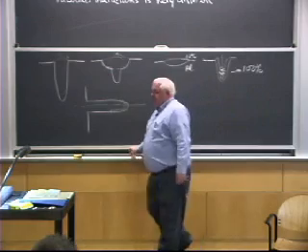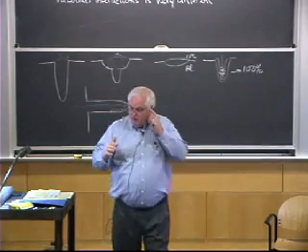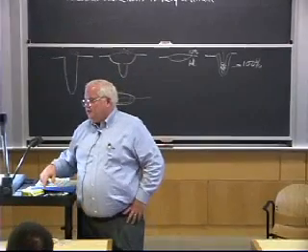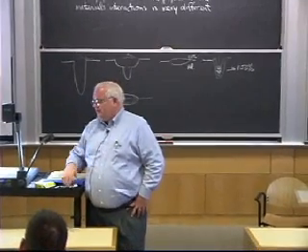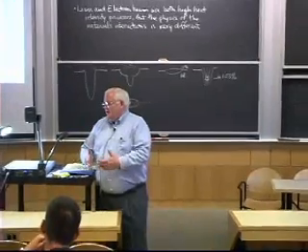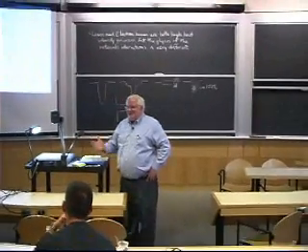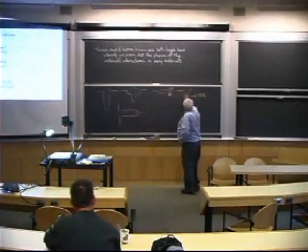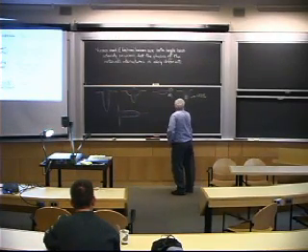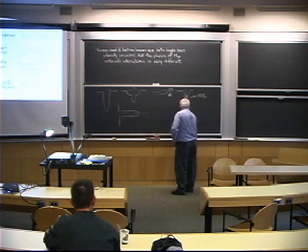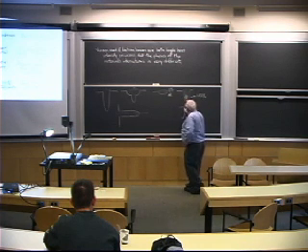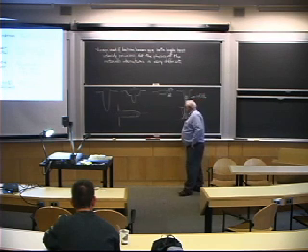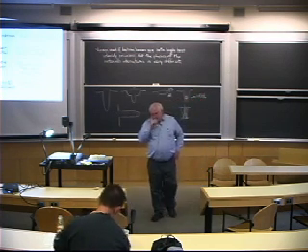So we did some experiments once years ago on laser welding of aluminum, and we showed that if you're just welding on a solid aluminum plate, which researchers like to do, why make a real joint? Why just melt something that's already joined together, and then when you're all done, you joined it together, right? Start out as a single plate. Well, it turns out you'll get this type of phenomena, but if you actually have a real plate that has a slight gap in it, and you get your laser light in here, you actually can melt something fairly deep because you got a cavity, okay? And you get higher absorptivity.